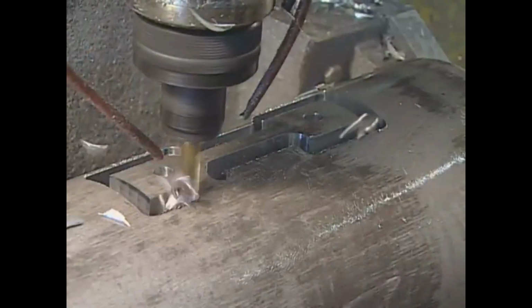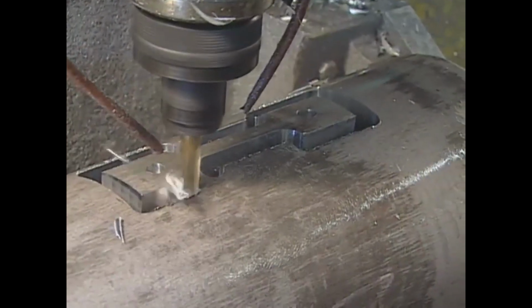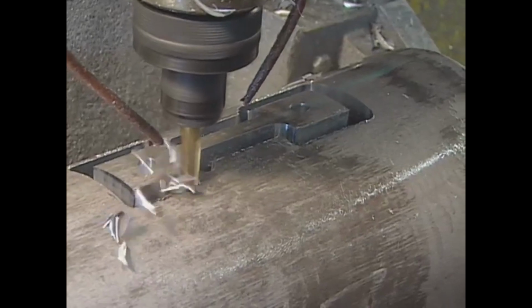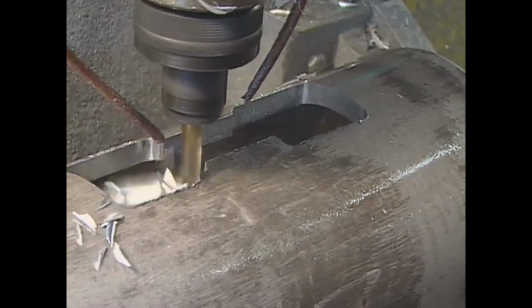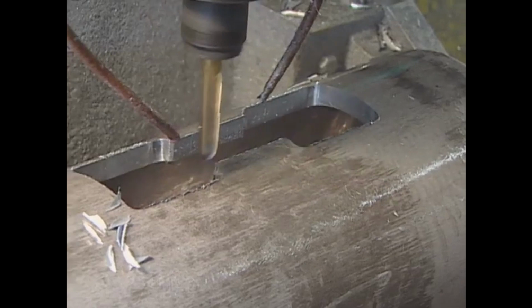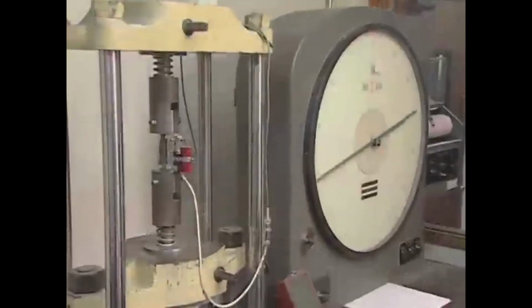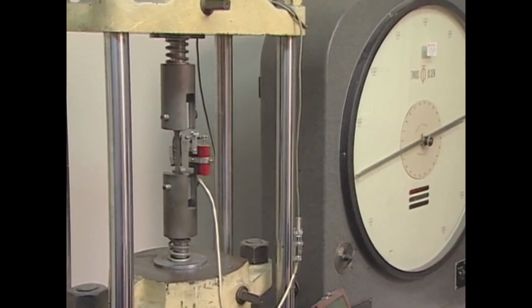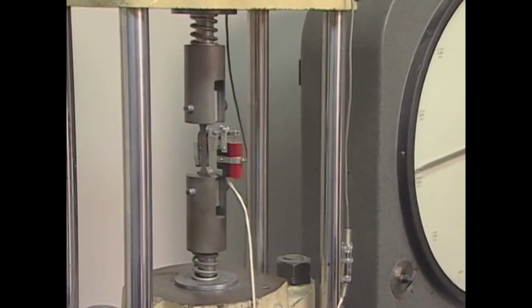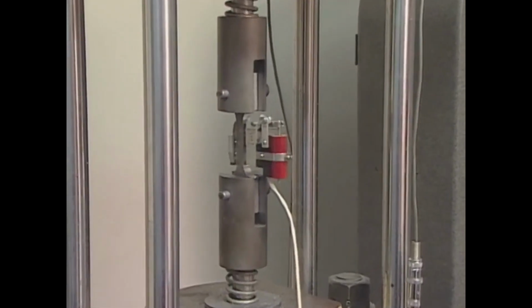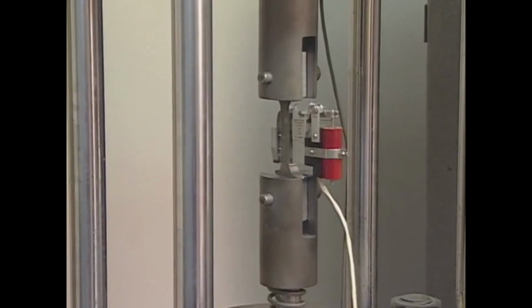After hardening, 1 of every 200 tanks goes through tests that determine the tank's tensile strength. To conduct the test, a saw removes a coupon or portion of the tank. A 27,240 kilogram, 60,000 pound tensile strength machine pulls the coupon apart. The aluminum must not break prematurely.